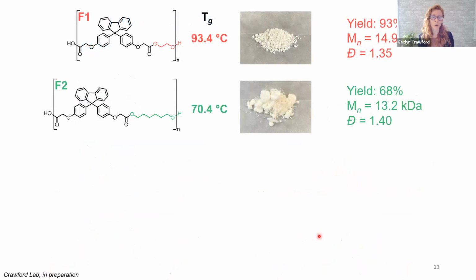Now that Tg, or glass transition temperature, is important because it represents the upper service temperature available for a product. And this is important in the industrial processing of these materials. And so the glass transition temperature here for the initial two materials is about 93 and 70 degrees Celsius. So that's much higher than room temperature.